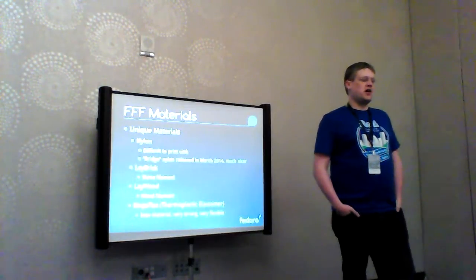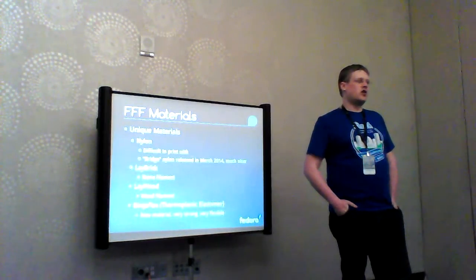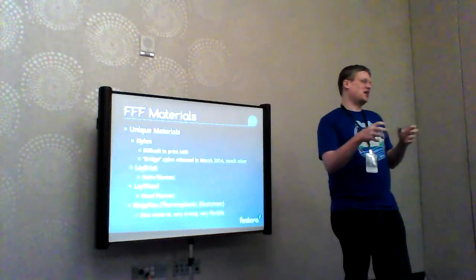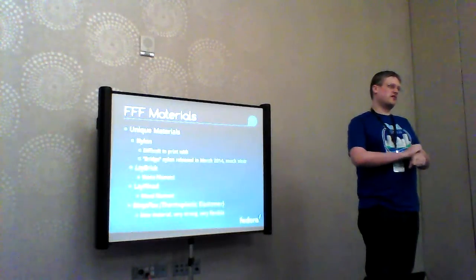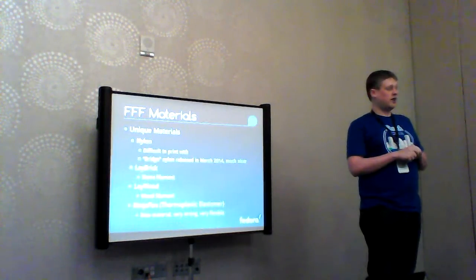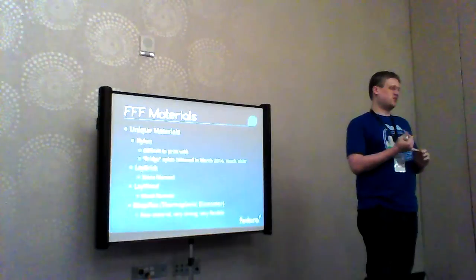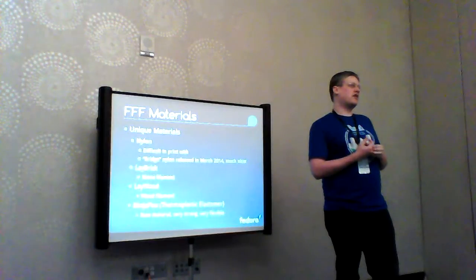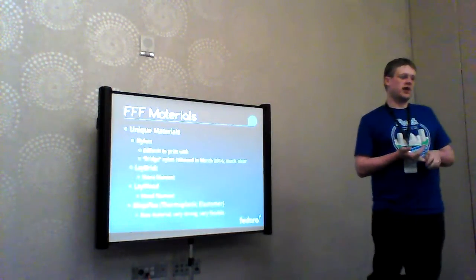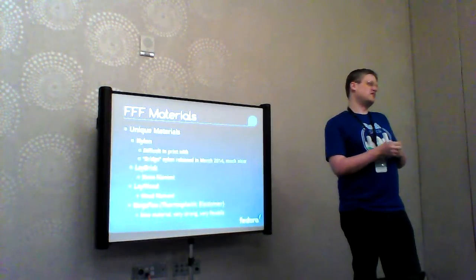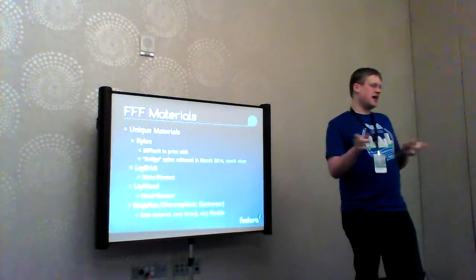Laybrick is a stone filament — the manufacturer pulverizes stone to dust, mixes it with a plastic solvent, and strings it into filament. When you print it, most of the plastic burns off and you're left with majority stone dust, giving you an object with the feel and texture of stone, though not the same strength. Similarly, Laywood is wood pulp mixed with plastic — most plastic burns off, leaving wood. You can even adjust the heat during a Laywood print to add wood grain to the model.